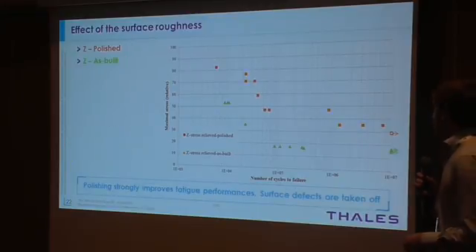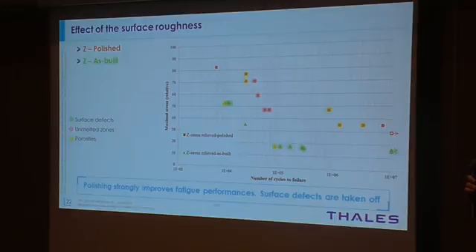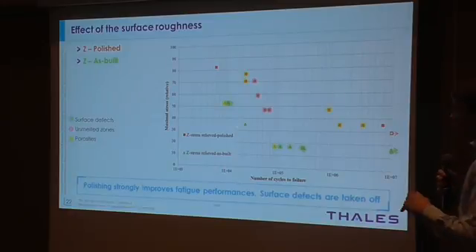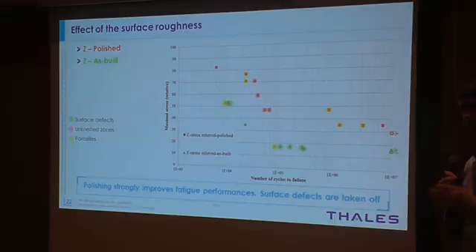Then we take the effect of the roughness. So again, as-built specimens almost always fail from surface defect due to the high roughness of the surface. It's about 35 microns, as Matteo said. And when we machine the specimens, we get rid of this surface defect, and we have higher fatigue properties.